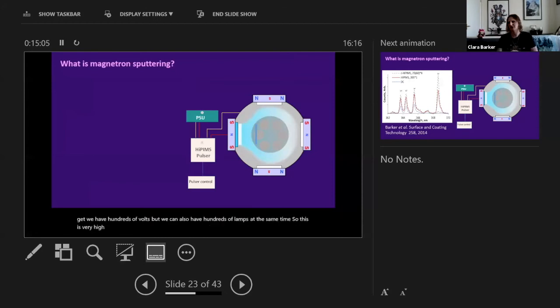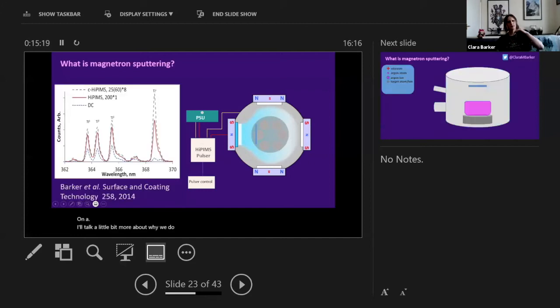And we have pulses of maybe 100, 200 microseconds, but then we have a long off period. This gives us a low duty cycle of around 1%. I'll talk a little bit more about why we do that. But one of the main things we can do is knock off not only atoms of the target material, but ions of the target material. We're hitting it with enough force that we're ionizing this target material. So when it lands on the substrate, it's got a lot more energy. This is really interesting, and it allows us to really tune the properties of the structure.